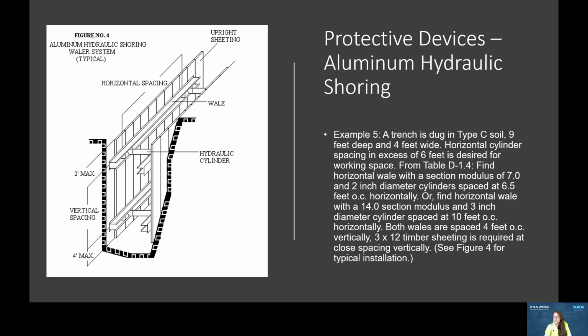Example 5. A trench is dug in Type C soil, 9 feet deep and 4 feet wide. Horizontal cylinder spacing in excess of 6 feet is desired for working space. From Table D-1.4, find horizontal wale with a section modulus of 7.0 and 2-inch diameter cylinders spaced at 6.5 feet OC horizontally, or find horizontal wale with a section modulus of 14 and 3-inch diameter cylinders spaced at 10 feet OC horizontally. Both wales are spaced at 4 feet OC vertically. 3 by 12 timber sheeting is required at close spacing vertically. See figure 4 for typical installation.